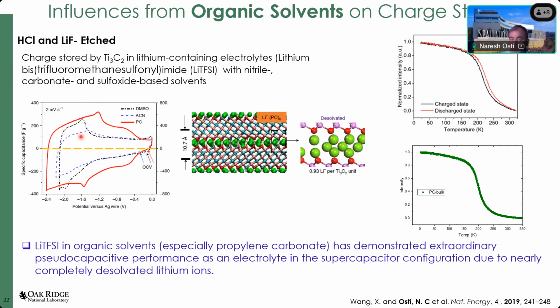That's what we found. And then we looked at the in situ XRD profile and also with the help of the MD simulation. It turned out that in this system, during charging, the lithium ion gets desolvated from the solvent molecules by itself. That means once you charge it, only the lithium ion gets in between the layers, not the propylene carbonate. So if that's the case, we thought, okay, if propylene carbonate is not getting in between the layers, that means it should show some sort of bulk properties. That's why we collected the